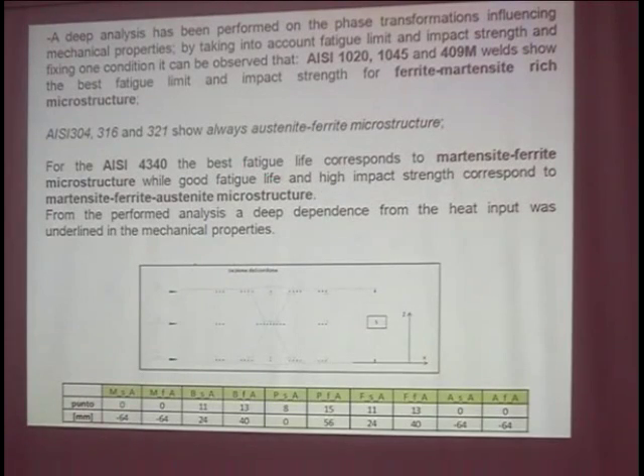So, for example, for AISI 1020 and 1045 and 409M steel, the welds show the best fatigue limit and impact strength for ferrite martensite rich microstructure. So if you are able to set your processing parameters to induce a ferrite martensite microstructure, you have the optimal situation in terms of mechanical properties. For such stainless steel, it is difficult to relate to microstructure evolution, because it is always the same. And for AISI 4340, the best fatigue life corresponds to martensite ferrite microstructure, while the good fatigue life and high impact strength correspond to martensite ferrite austenite microstructure.